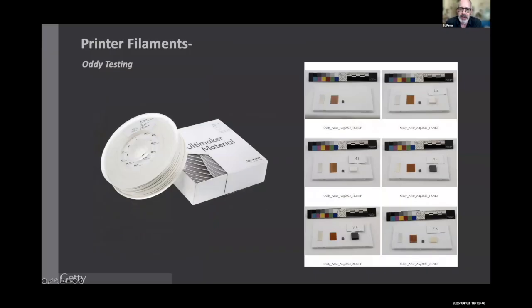All of the object models are printed using PLA plastic, which is very easy to print with and is recyclable. Unfortunately, it doesn't pass Oddy tests. Based on other listed Oddy tests, ABS plastic seems to pass. We've tested both a white and a black ABS filament from a company called Ultimaker. The black did not fully pass, but the white did, fortunately.